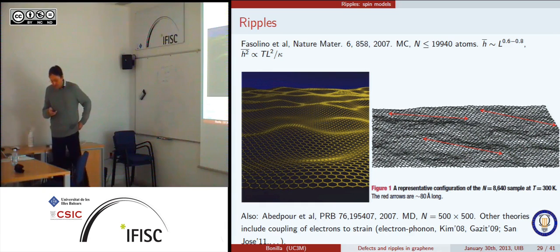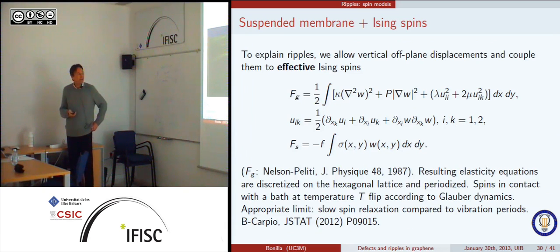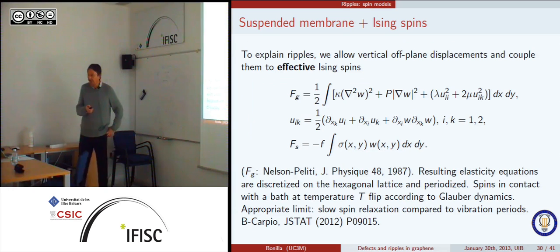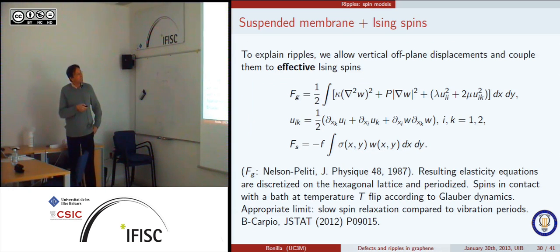explanations. We wanted to see whether we understood something about the dynamics. So this is something we tried. We are not totally satisfied with it at all. But what we did, we took just the energy of a membrane. So this is the linear elasticity part on the plane of the membrane. Here you have the bending contribution. So this is suspended, and you can buckle the membrane in the vertical direction, not only the horizontal. So this is the buckling part. W is the vertical component. The gradient of the displacement essentially contains a nonlinear part in the vertical direction.